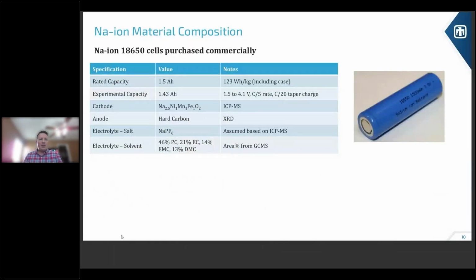So the iteration that we got is what's shown here. We received these at 1.5 amp hours. We tested them. They came out experimentally at 1.43 amp hours. If you look at that in terms of energy density, you get 123 watt hours per kilogram. That's with the case. However, if you're not familiar with these numbers, that's pretty substantially lower than a modern commercial lithium ion.